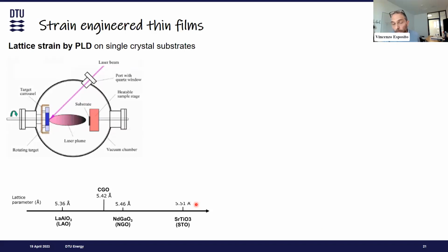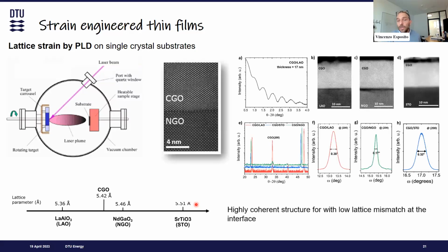However, we still need to produce some samples, and to do that, we go away from a classic processing technology for PVD or CVD, and we go for still PVD technology that would allow us to control with great precision the composition of the crystal, especially the orientation of the crystal. We are specialized here in using pulsed laser deposition for thin films. And this allows us to create a very nice interface between substrates, which are single crystal. In this case, for example, we have a neodymium gallate single crystal with the cerium oxide deposition. What is nice in this case is that we have basically a single crystal deposition on a single crystal substrate, which has no electromechanical activity whatsoever.